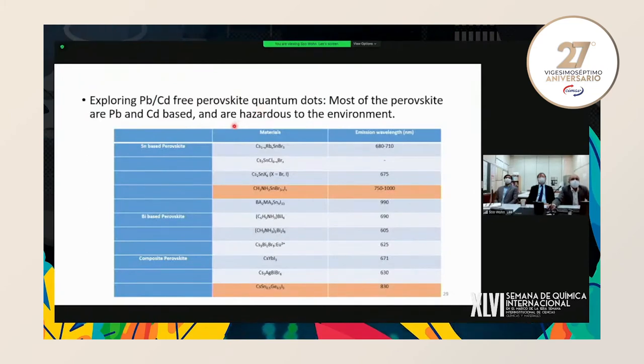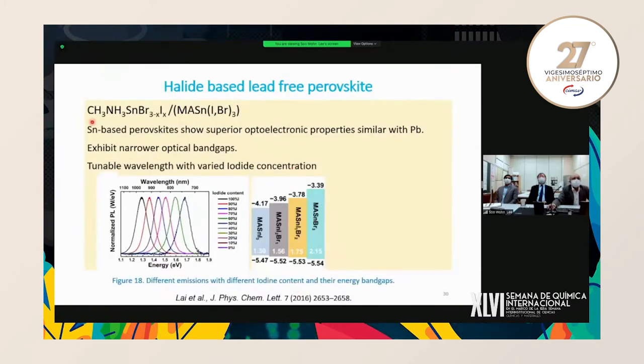So as we know, most of the perovskite quantum dots are based on lead and cadmium. So there are few materials without lead and cadmium. Here are some lists. So most of them are containing cesium, and here we have methylammonium tin halide material, which has emissions from around 750 to 1000 nanometers. So it will match the absorption of silicon solar cell. So this material can be considered for future LSC. Similarly, another material is cesium tin germanium iodide. So here, why do we consider this methylammonium tin halide material for future LSC?